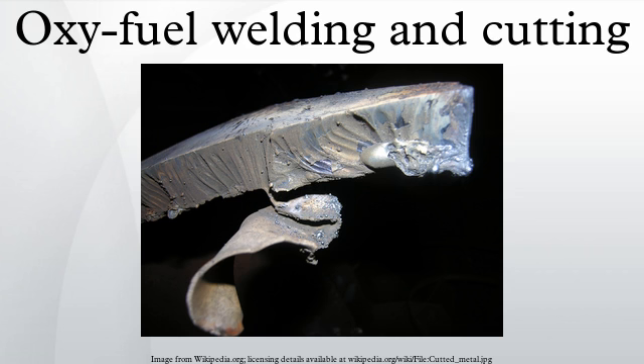An excess of acetylene creates a carburizing flame. This flame is characterized by three flame zones: the hot inner cone, a white-hot acetylene feather, and the blue-colored outer cone. This is the type of flame observed when oxygen is first added to the burning acetylene. The feather is adjusted and made ever smaller by adding increasing amounts of oxygen to the flame. A welding feather is measured as 2x or 3x, with x being the length of the inner flame cone. The unburned carbon insulates the flame and drops the temperature to approximately 5,000 degrees Fahrenheit. The reducing flame is typically used for hard-facing operations or backhand pipe welding techniques.